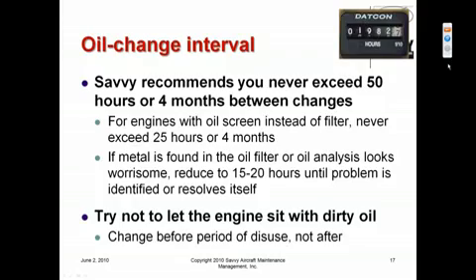But there's a finite quantity of the acid neutralizer, and if you allow too much acid buildup, the oil will start getting acidic and will start having a corrosive effect on expensive things like crankshafts and camshafts and stuff. So we don't want to see dirty oil sit in the engine for too long. So our recommendation is to change the oil at 50 hours or 4 calendar months, whichever comes first.